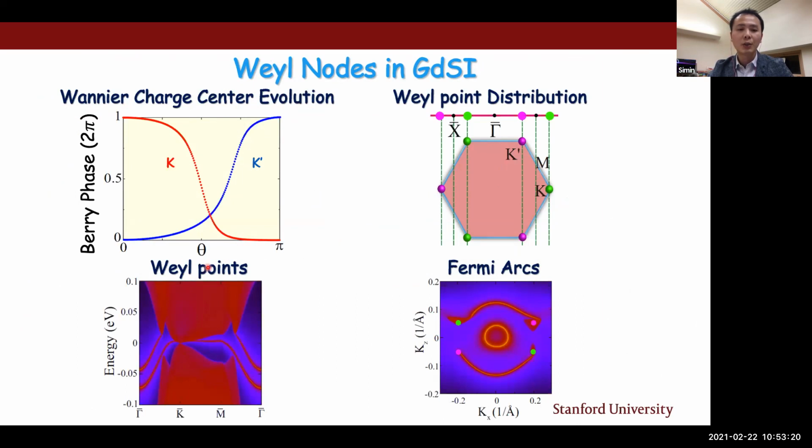On the 001 top surface, we can find the Weyl points are projected to the K-bar point, leading to this kind of gapless dispersion. On the 010 surface, we can find very clean Fermi arcs. So gadolinium sulfur iodide is the long-pursued ideal Weyl metal with the Fermi level at the Weyl point.